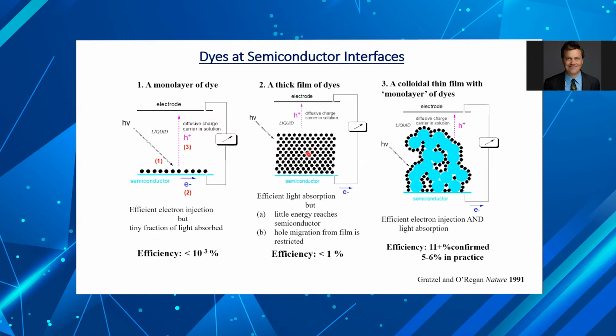The other challenge has been that if the dye does get to the semiconductor interface to separate charge, then once it injects an electron, you create an oxidized dye in an environment where the oxidized dye is not well stabilized. It's typically a very low dielectric environment, and those are conditions that can promote very rapid back electron transfer. So, well, there are people, particularly in the organic photovoltaic field, that are still working on this type of approach, particularly when you want to harvest all of sunlight.